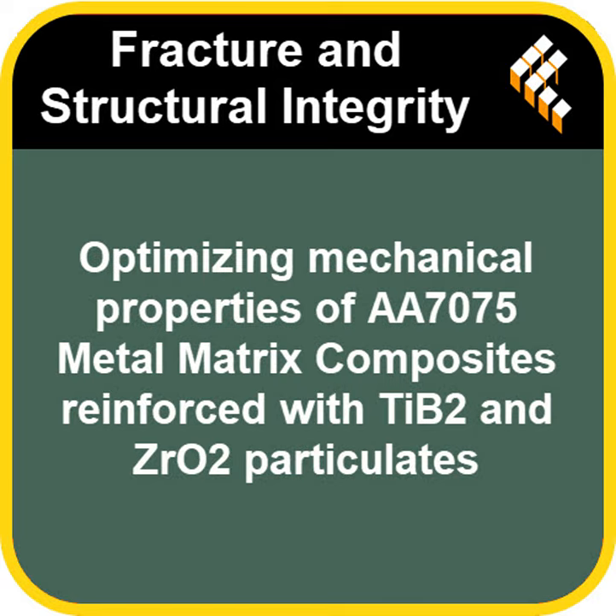Correct. It's a solid improvement. The 2% ZrO2 composite reached 113 MPa, so a smaller increase. And interestingly, the 6% ZrO2 composite actually saw a slight decrease in yield strength compared to the 4%, down to 110 MPa. Again, reinforcing that 4% sweet spot. Absolutely. It really highlights that optimal threshold for reinforcement loading and dispersion.